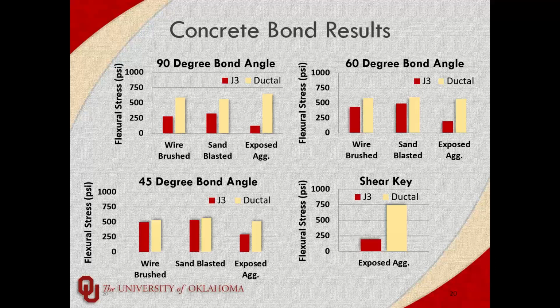surface of the UHPC. It really indicates that it's very important to maintain an SSD condition when bonding UHPC, especially J3, and it's mainly due to the lower water cement ratio. There's not as much, really any free water floating around in UHPC, so whenever it comes into contact with a dry concrete surface, it's going to suck whatever moisture it can out of it, and so the SSD condition will reduce that dramatically. So we found that SSD is really important for J3.